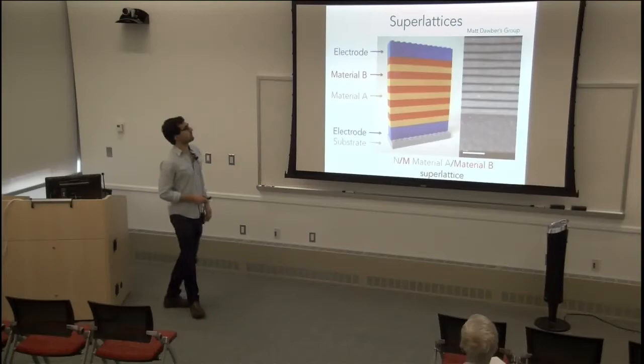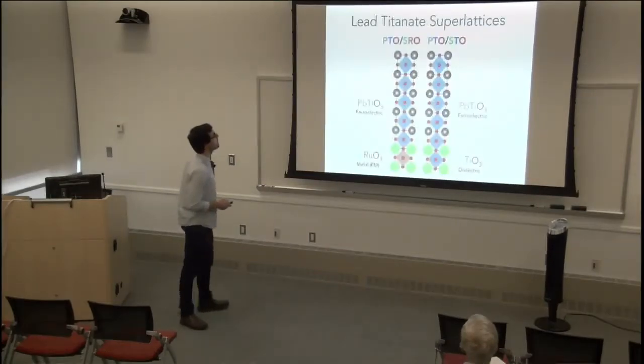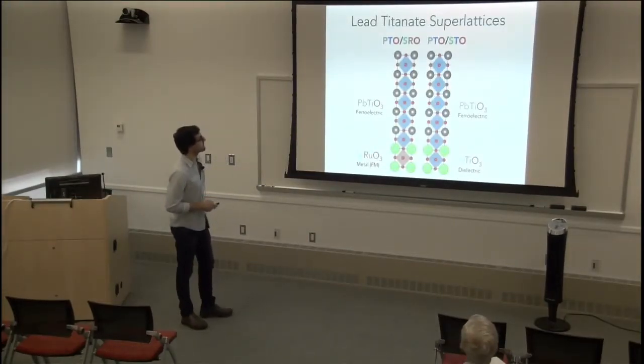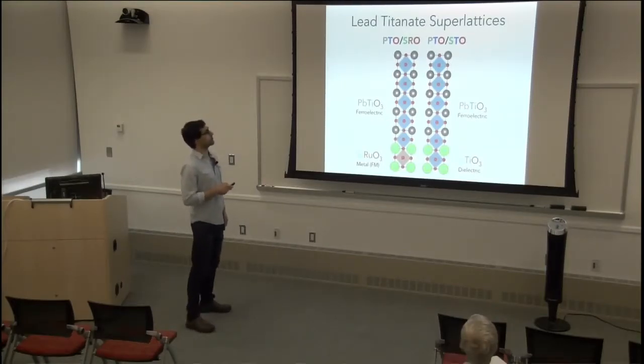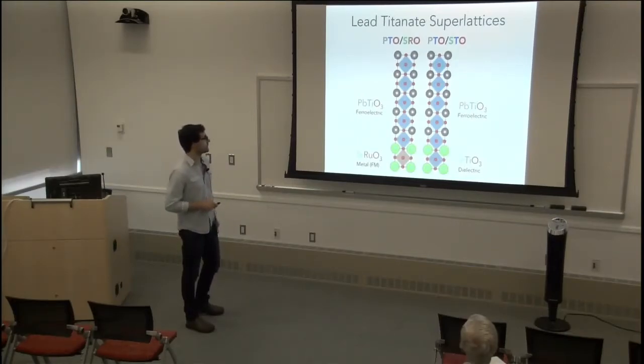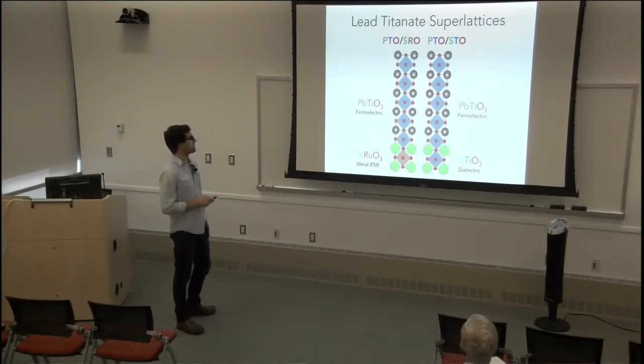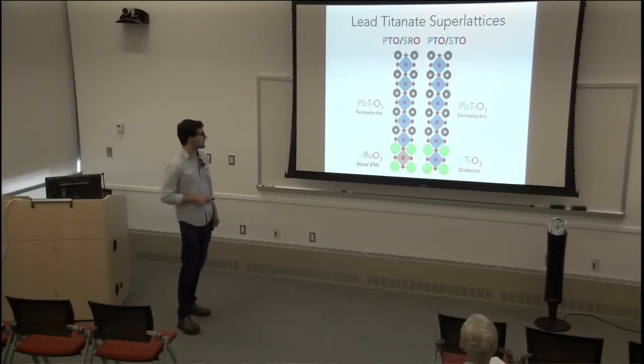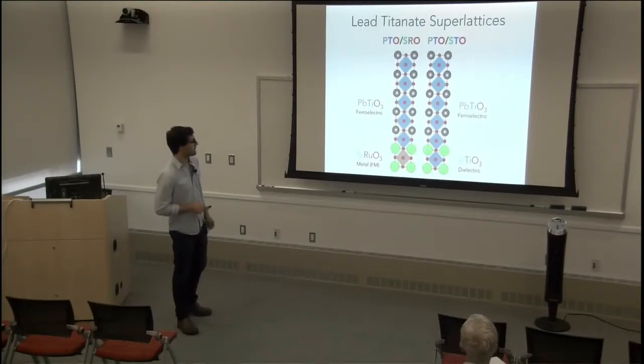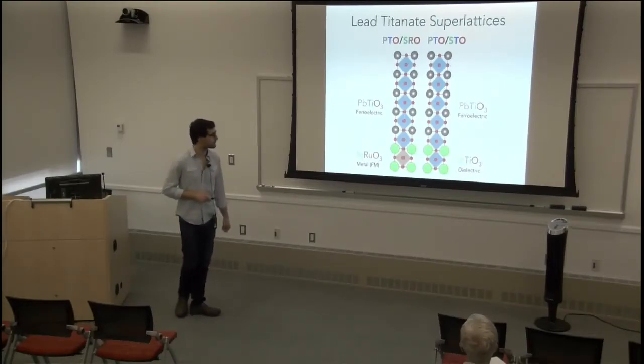So specifically, the type of superlattices we are interested in are lead titanate-based superlattices. And I'm going to talk today about two types of these lead titanate superlattices. One is lead titanate strontium ruthenate here on the left. Lead titanate is your ferroelectric, and you see this is the perovskite unit cell that we talked about before. And strontium ruthenate is a metal. If you have enough layers, here I only have one layer, so it's just a regular metal. If you add more layers, it could potentially be a ferromagnet.